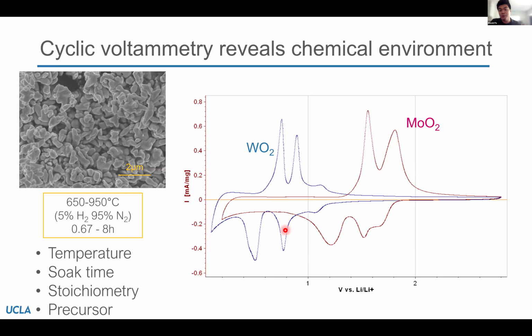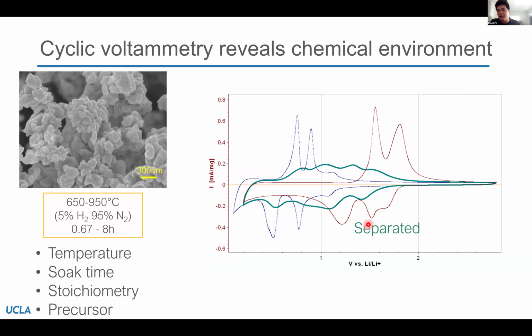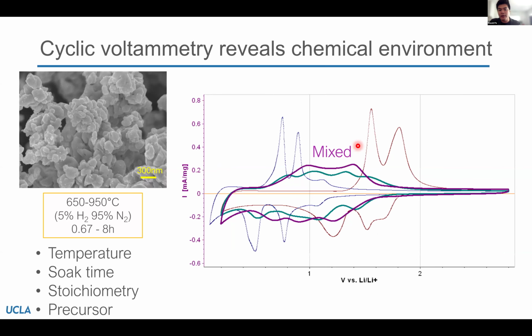And so what we could expect when we mix these two materials into a solid solution is, if we have a nano-separated material, we'll see something that looks more like a combination of the two, with well-defined peaks spread across this whole voltage range. And indeed, that is what we see when we make a separated solid solution, again using some of those turning the knobs in our synthesis. We can see that we have well-defined peaks that are shifted inward, which is indicative of transition metal mixing. However, we can see that they are close to their single element counterparts,